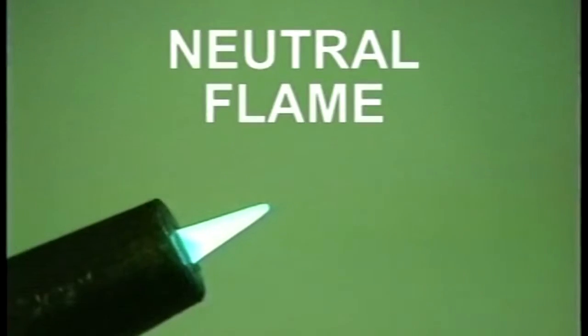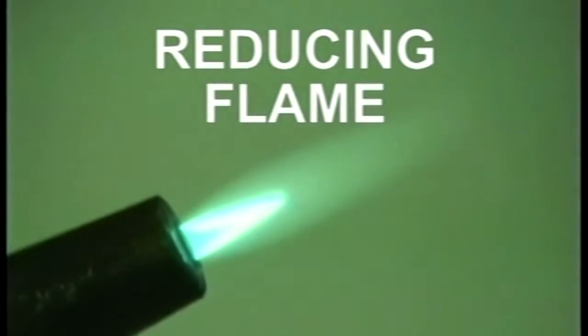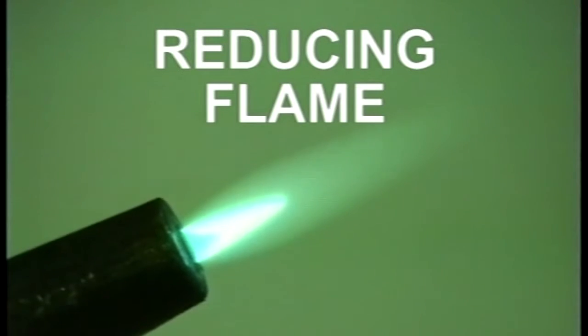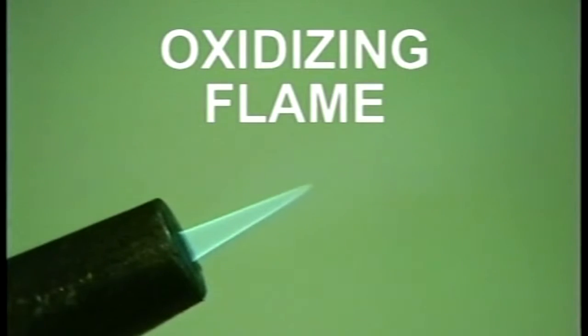This chemical reaction produces carbon dioxide and purges air away from the molten metal. When you have a neutral flame, this chemical reaction happens just like it's supposed to. With a reducing flame that has an excess of acetylene, carbon molecules can be deposited in the molten puddle, making the weld brittle. An oxidizing flame with too much oxygen can oxidize or burn the puddle, possibly leaving porosity. So here again, always adjust the torch to a neutral flame.